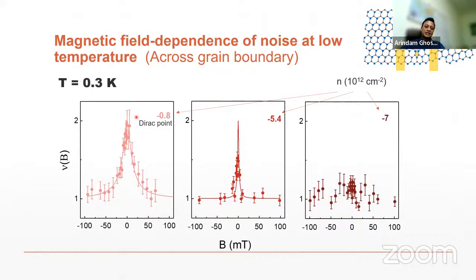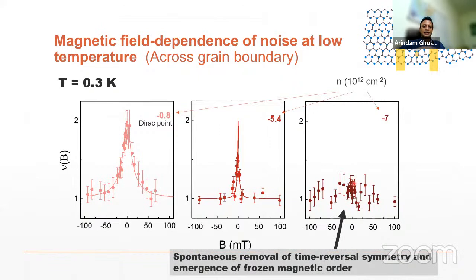But when I go to large densities, the noise no longer comes down by a factor of 2, which means that the spontaneous removal of time reversal symmetry and possible emergence of magnetic order is not only at low temperature, but also at high density. So that gives us a possibility of looking at magnetism that is driven by electric field.